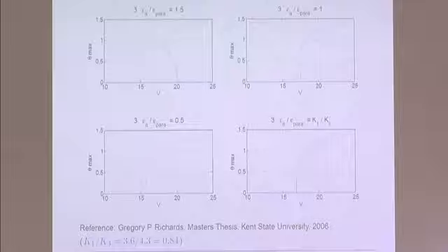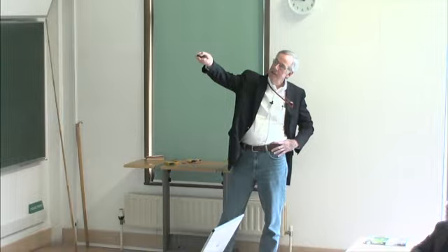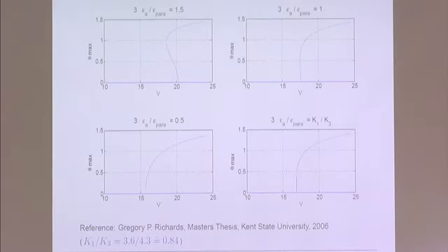I don't have all the stabilities and the free energy lines indicated here, but basically it's a subcritical bifurcation when this is larger than about 0.84. Here we're getting kind of close. Here I think is the precise crossover point where this is essentially opening to the right like a quartic instead of a parabola. And here we've gone over into the standard second order setting.